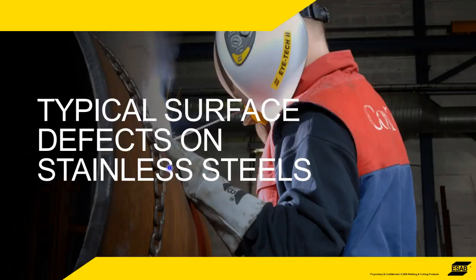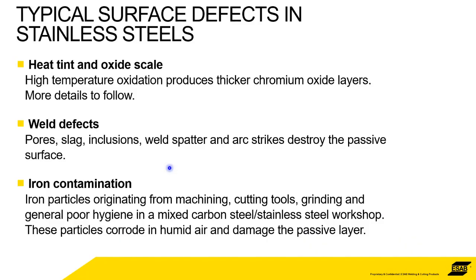So typical surface defects that will contribute to damaging this chromium oxide layer and making the stainless less corrosion resistant are things like heat tint and oxide. It's not just the appearance. High temperature causes oxidation of the base metal, and you get a thicker chromium layer, and it's the light diffraction through the thicker layers of chromium oxide that cause the tint. I've got a separate slide on that, so I'll talk more in detail about that later.